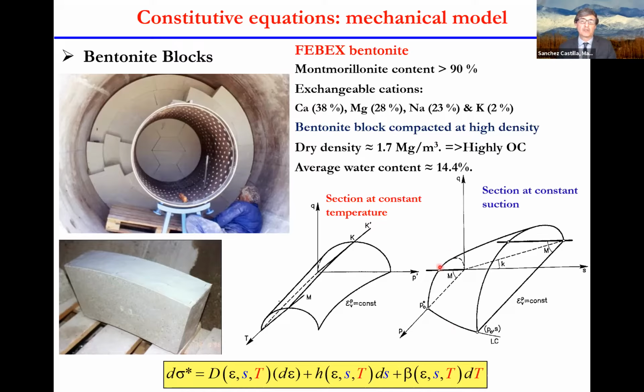What we see is that as the soil becomes more unsaturated, this elastic domain that defines the ellipse of the modified Cam clay model tends to expand and grow with this increase of the capillary pressure. And we also observe that if we increase the temperature, this ellipse starts to shrink, right? So it's possible to model that in the context of elastoplasticity, and we basically develop a model in which our stresses are updated depending on the change in strain, suction that basically involves liquid and gas pressure, and temperature, right?